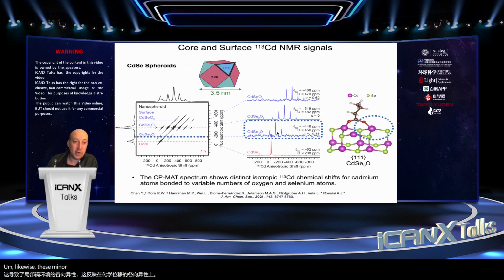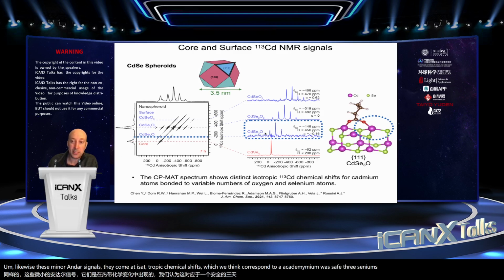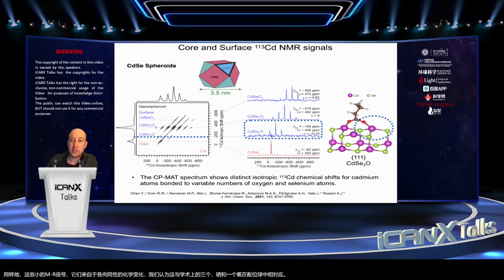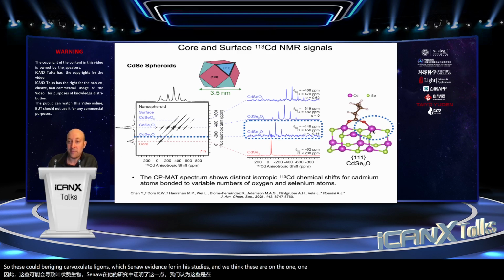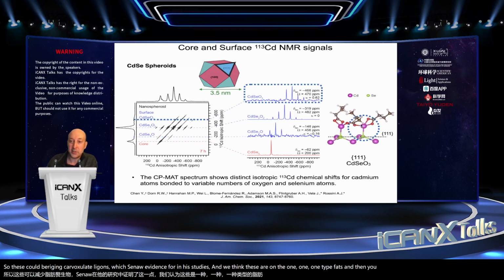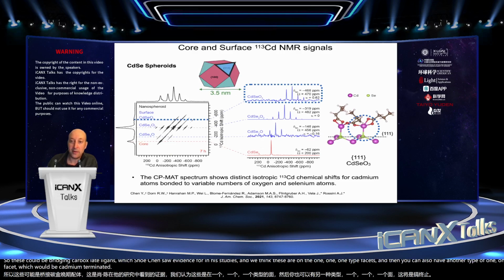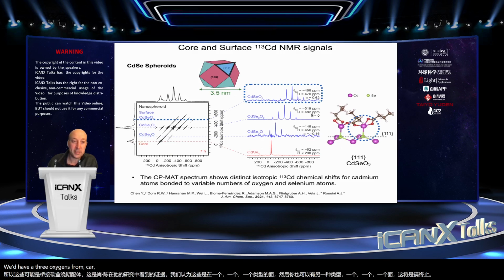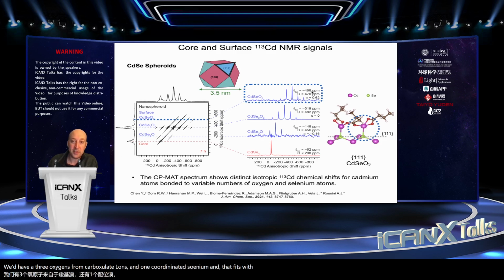Likewise, these minor NMR signals come at isotropic chemical shifts which we think correspond to a cadmium with, say, 3 seleniums and 1 oxygen in the coordination sphere. So these could be bridging carboxylate ligands, which Xu Chen saw evidence for in his studies. And we think these are on the 111 type facets. And then you can also have another type of 111 facet, which would be cadmium terminated. We'd have 3 oxygens from carboxylate ligands and 1 coordinated selenium. And that fits with this isotropic shift that we can observe here.